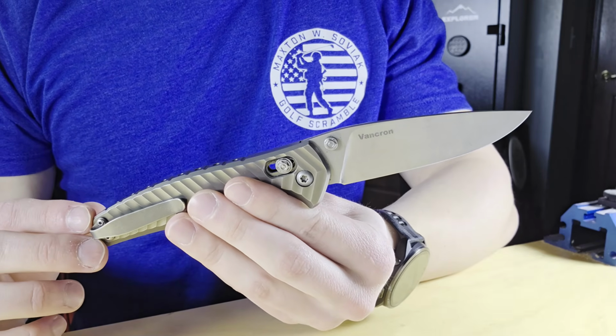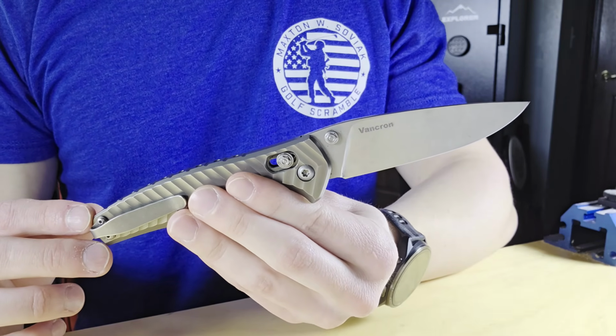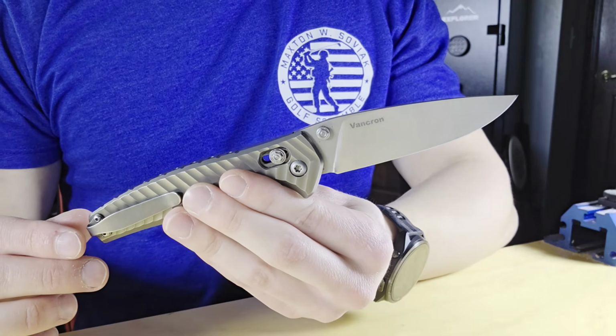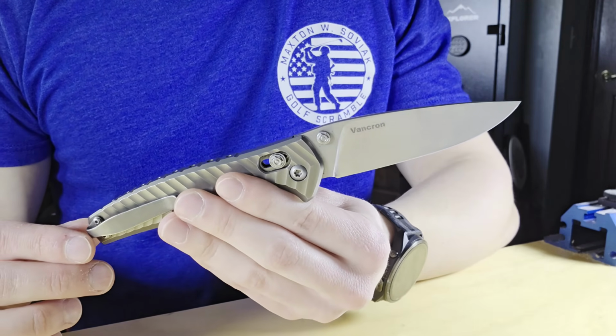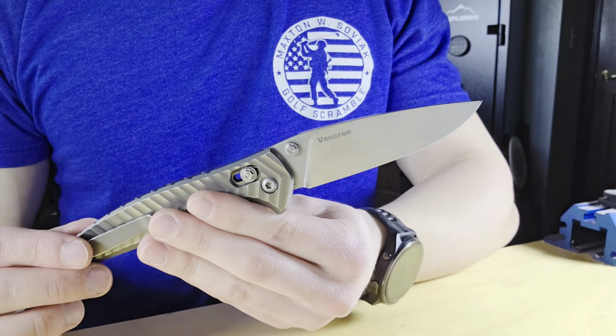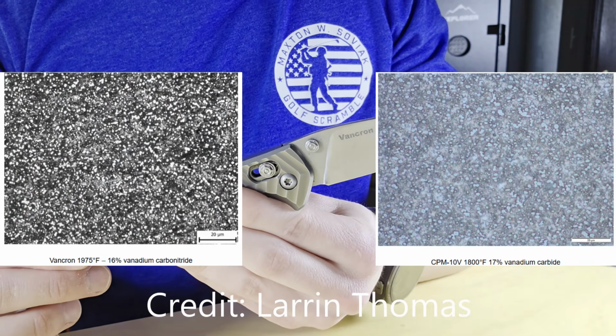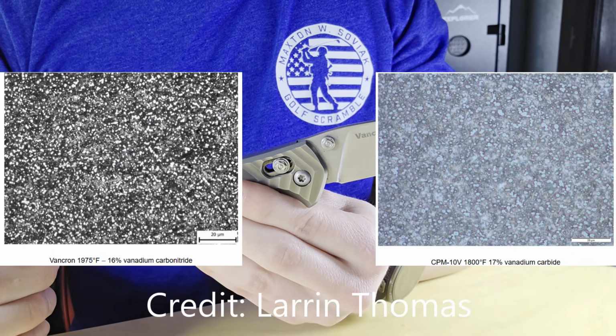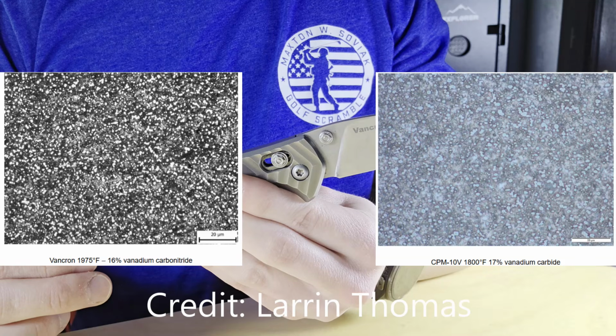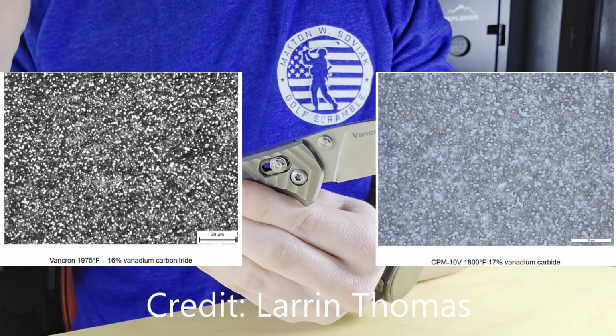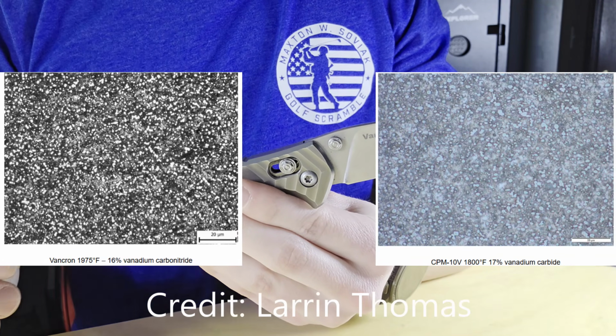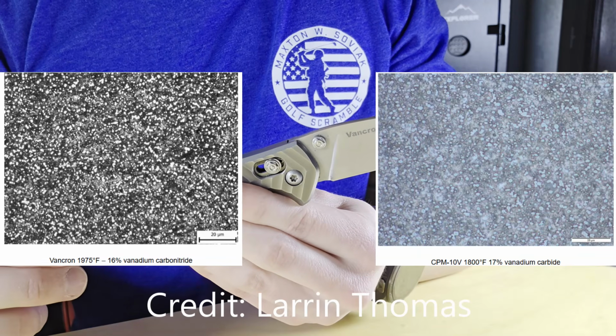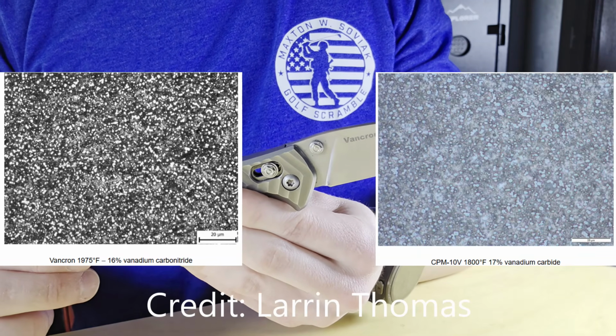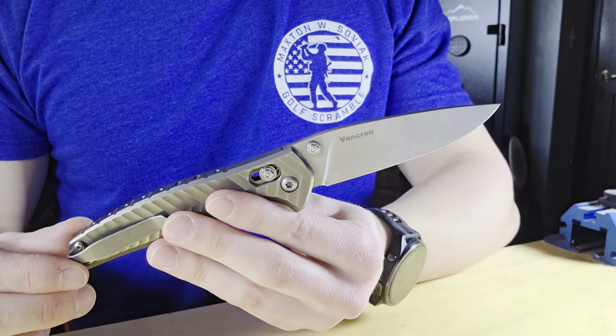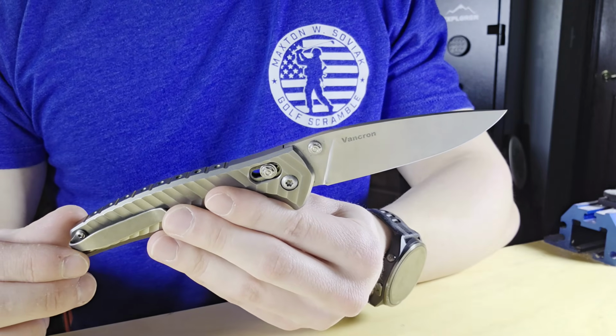So Vancron has that high vanadium combined with the carbon and nitrogen, and it creates something called vanadium carbonitrides, which is a little bit different than the vanadium carbides that you hear about. They're smaller than the vanadium carbide because the nitrides coarsen more slowly during the high temperature processing in production, and the total volume of the carbonitrides is about 16%, which puts it in the realm of like 10V and Vanadis 8 as far as total carbide volume goes.